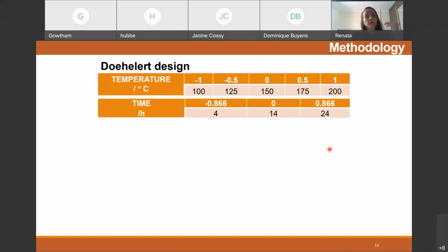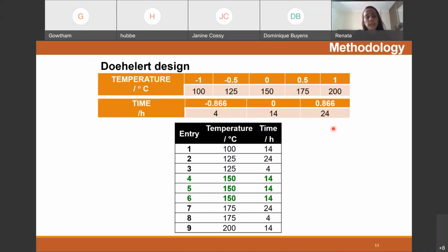For the experimental design, the temperature was studied from 100 degrees to 200 degrees, and the residence time evaluated in this process was from 4 hours to 24 hours. Then we did 9 experiments. These are the conditions evaluated in this design, and it is important to say that we did replicates in the central point.